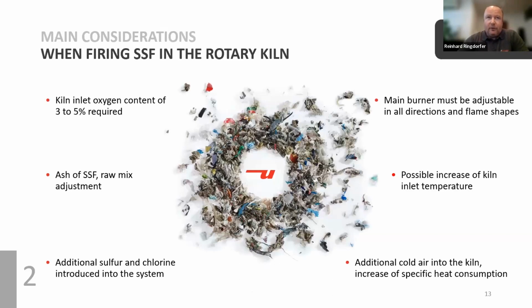So for most cement plants here in Europe, it's very common to know what to do when you fire secondary fuels, because they've been doing it for 2 or 3 decades. But there are some things which need to be taken care of when you want to start firing secondary fuels in the rotary kiln. First of all, compared to primary fuels, you need more oxygen content in the kiln inlet. We recommend 3 to 5% in the kiln inlet to ensure complete combustion, to ensure that you have no CO present at the kiln inlet.